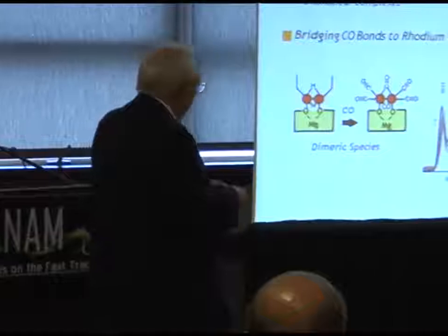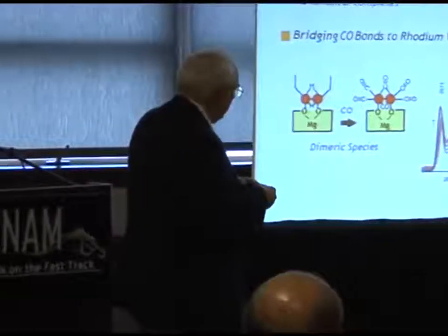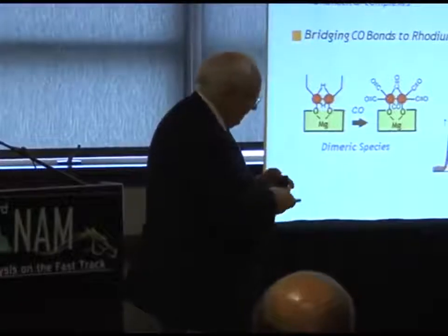And so if we're just, say, flowing hydrogen or butadiene in hydrogen, over time those CO ligands leak away, and the catalytic activity comes up. So we're going to be interested in using those ligands to try to steer the selectivity of the catalyst. So let's go back to this one, no carbonyls. Let's say it's not very interesting. This is the butane, selectivity versus conversion. This is the butane, and this is one of the butenes.